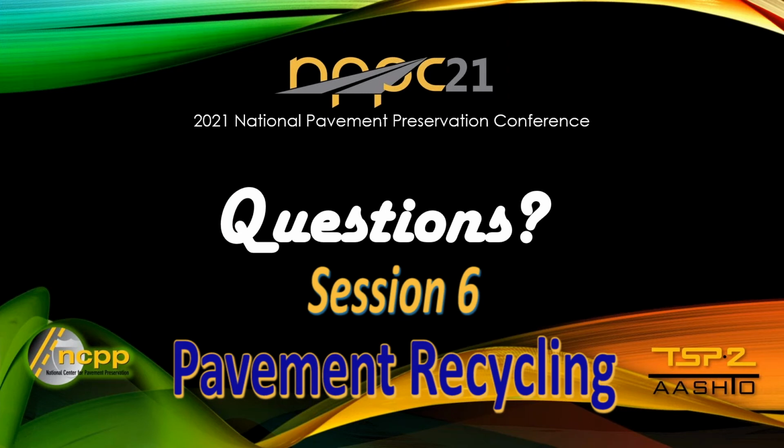For the CIR process, I would say a lot of the rural projects we get the opportunity to be involved with, oftentimes there's chip seal. I mean, it's almost common. When there's an excessive amount or just consecutive chip seals, that's where the material scoping and the mix design process might help better understand if some of the other additives are needed, particularly corrective aggregate and or some other type of additive like a cement to help maybe neutralize some of the excessive asphalt in there. I haven't seen a project where you need to mill off the chip seal to do a successful CIR to date.